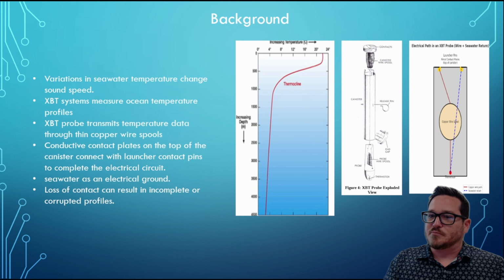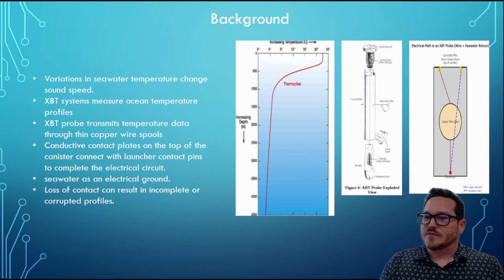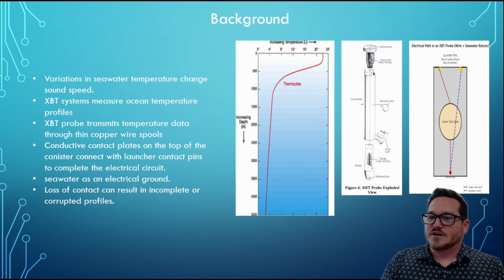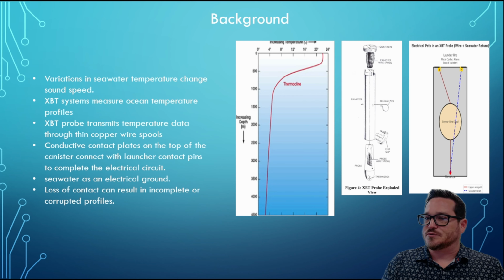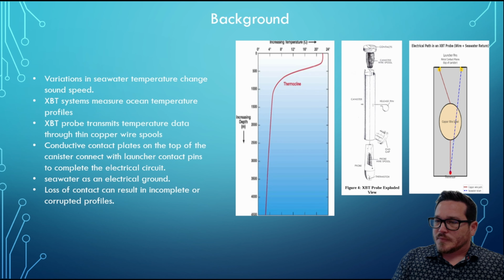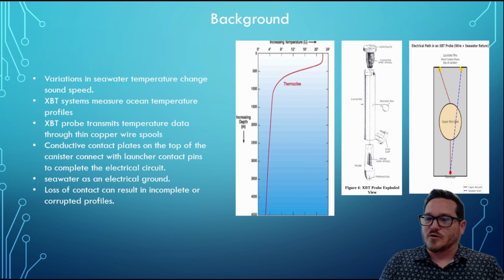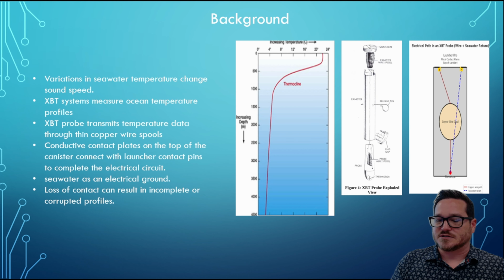During deployment, the XBT probe detects temperature data with its thermistor and transmits that data through thin copper wire spools contained inside the probe canister and the probe itself. Conductive contact plates on the top of the canister connect with the launcher contact pins to complete the electrical circuit. The system uses seawater as an electrical ground, creating a closed circuit between the launcher and the probe during deployment. Reliable electrical contact is critical for continuous data transmission throughout the probe descent. Loss of contact can result in incomplete or corrupted profiles, reducing the accuracy of sonar performance predictions and environmental assessments.